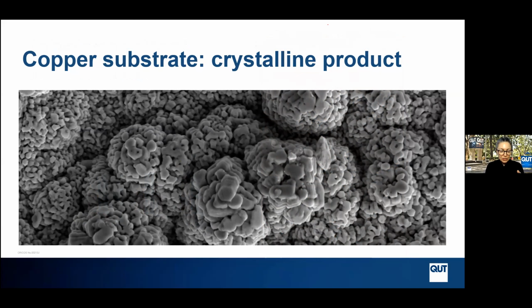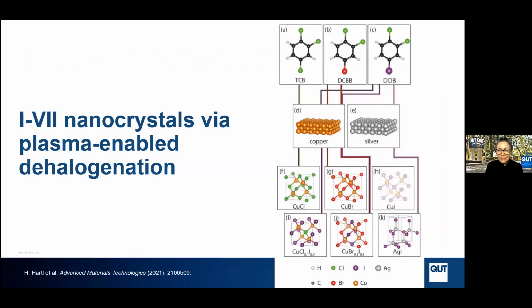The dehalogenation should have led to a heavily cross-linked organic polymer, and this is what we measured using TOF SIMS and a few different techniques, was essentially that we had created sort of a dense carbon-based polymer mesh. When we started getting crystalline products, we really didn't know what was happening. As it turns out, what we were doing was facilitating the synthesis of cuprous halide nanoparticles through this process. So our dehalogenation byproducts, the chlorines, the bromines, the iodines, you'll notice we're using a whole selection of molecules now, we're reacting with the substrate to allow the synthesis of these nanoparticles. These are really interesting materials, the I-VII semiconductors. These cuprous halides are transparent p-type semiconducting materials that have a lot of really interesting intrinsic properties. So it was a real treat to find such a fast and easy way to synthesize them.